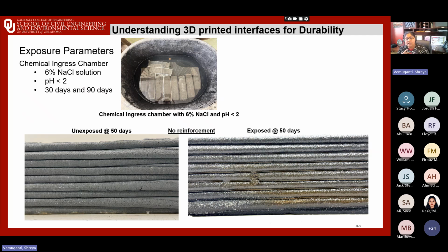So what we did here is, in all the rest of the slides, you'll have the left or top slides to be the unexposed and the right side would be the exposed. Okay, so these are chemical ingress related specimens, 6% NaCl solution, maintaining pH less than 2 every single day. We are trying to understand 30-day and 90-day exposure. Here are the 50 days physical observation. We took them out of the chemical ingress chamber, took pictures for this particular presentation, and we put them back. So they are sort of wet.